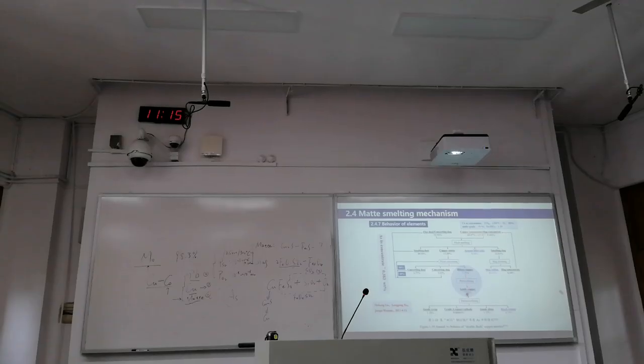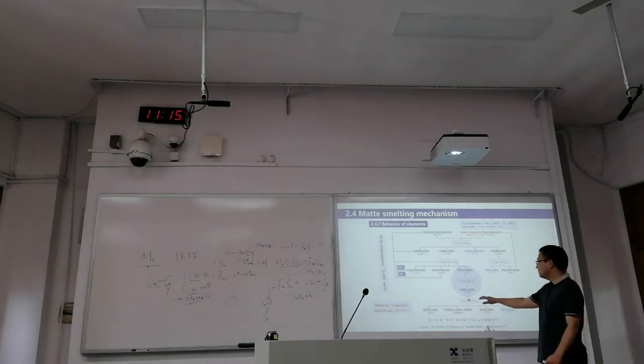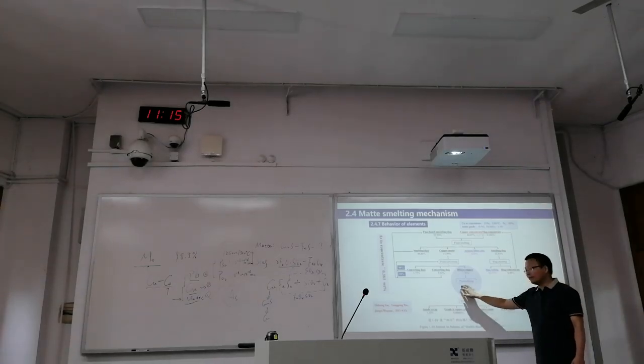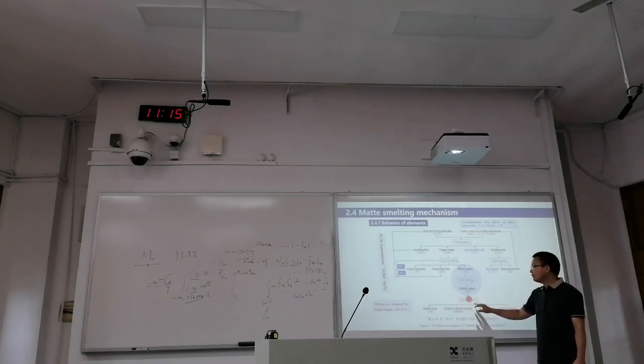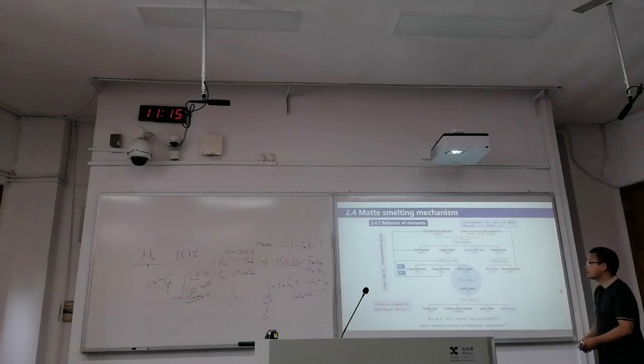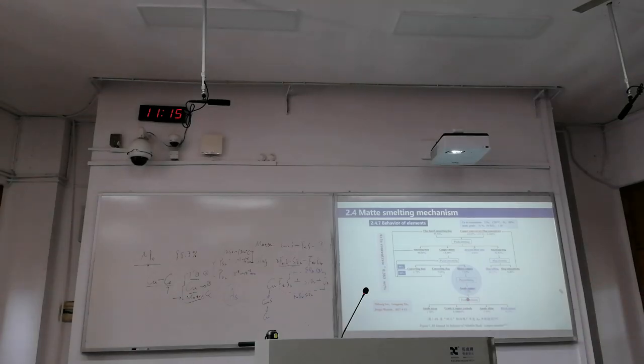7.3%. What does it mean? You are not removing arsenic anymore. Arsenic is so stable in copper. So you have no idea how we can get rid of that. So when arsenic moves together with copper, you have to go to the electrical refining. So you are going to this part, and 7% will enter this part.